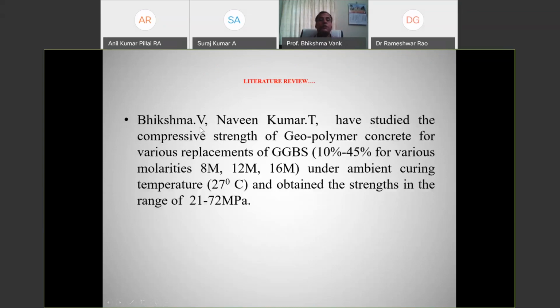This work was done at Osmania University by myself and my research scholar Naveen Kumar. We replaced GGBS from 10% to 45% for the grades of concrete M20 to M60, and molarities of 8, 12 and 16 molarity have been taken. This work is not with temperature. It is under ambient curing, 23 to 27 degrees, the room temperature only. We obtained strengths of 21 MPa to 72 MPa, which is equivalent to nearly M20 to M60.